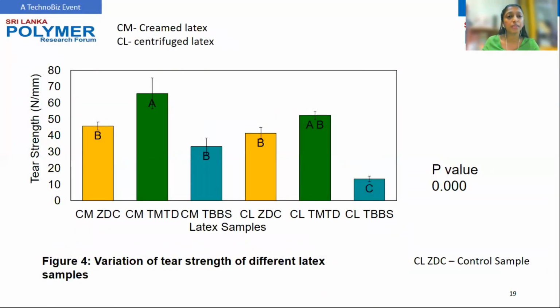Similar to the tensile strength, cream latex based films have shown higher tear strength values than the corresponding films made out of centrifuge latex, as in figure 4. A significant reduction in tear strength of both TBBS systems is also evident, similar to the observation made in their tensile properties when the accelerators are considered. Cream latex TMTD has the highest tear strength, which means it has the highest level of resistance to crack propagation in the latex specimen.